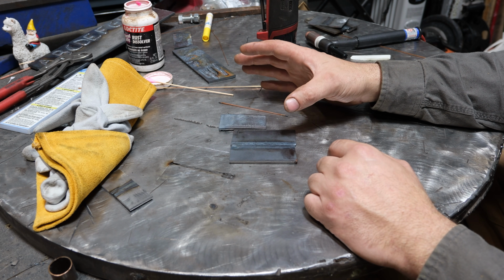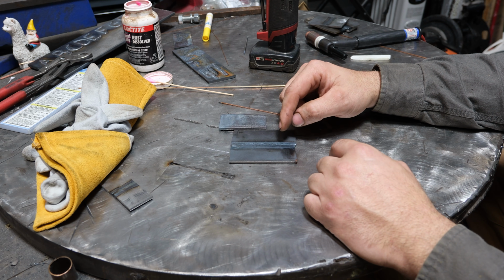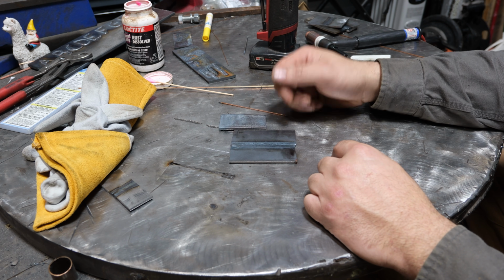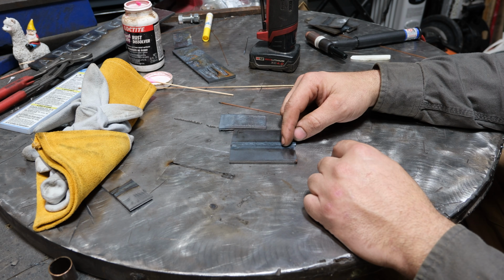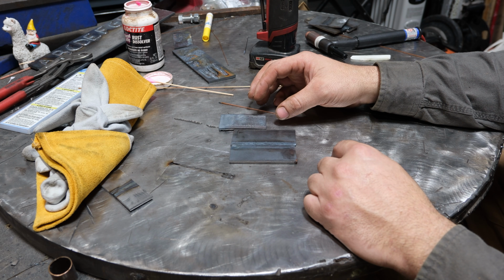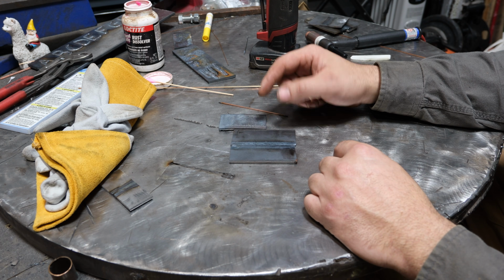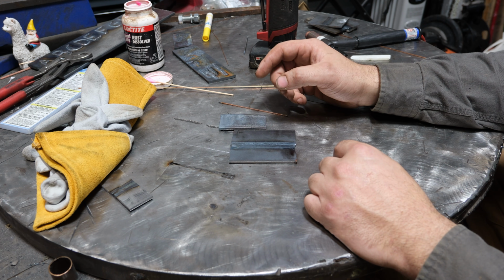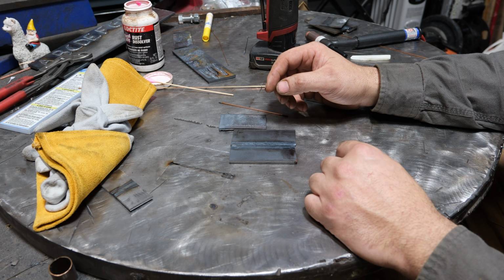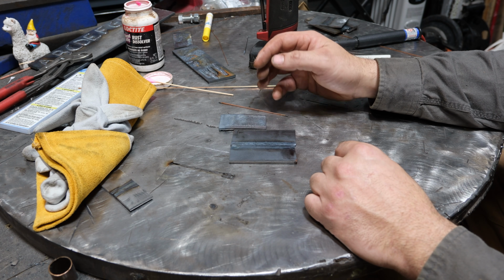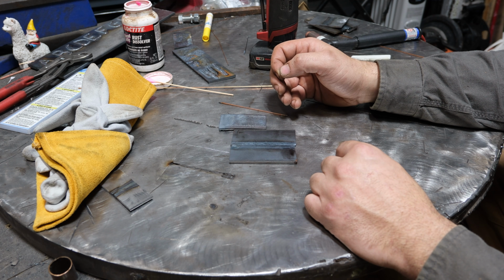Now, on that topic, I can't stress enough how important it is to have proper argon shielding, aka you don't have leaks in your system, you're using 100% argon and your flow is high enough, because the molten pool will react with oxygen if you don't have proper argon coverage, and that will also make your welds look poor.